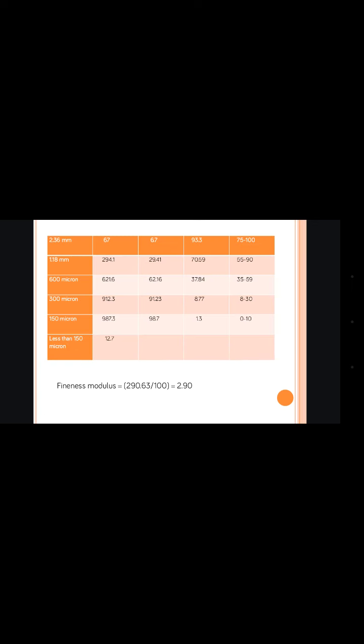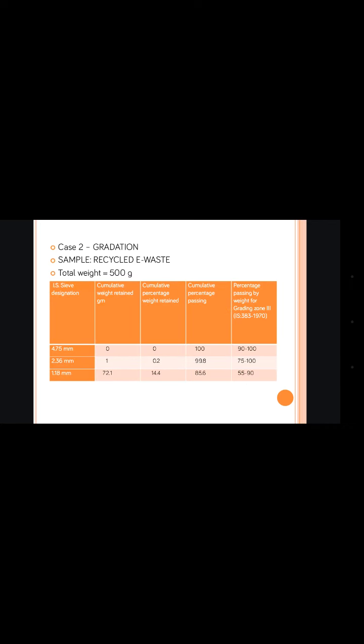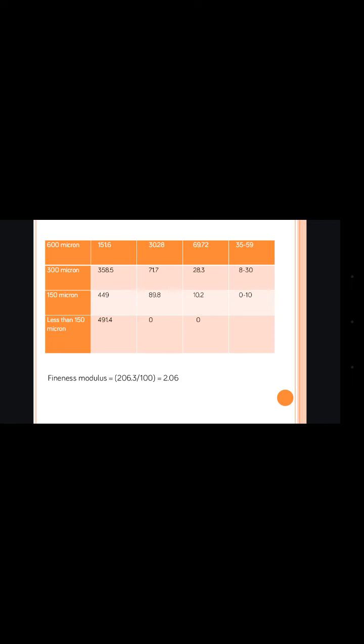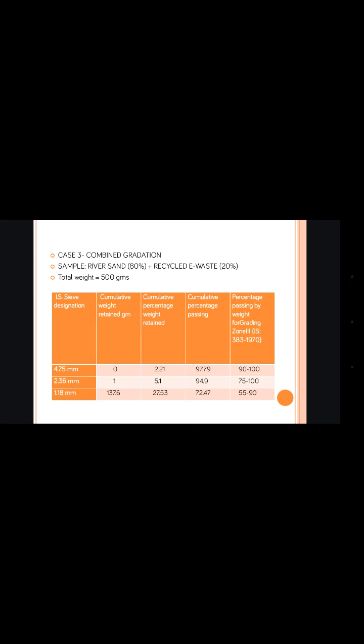The sieve analysis was taken for various cases. The first case was for river sand. The fineness modulus obtained from this is 2.9. In the second case, the gradation was taken just for recycled e-waste, and the fineness modulus was about 2.06. In the third case, we combined the gradation. We took 80% river sand and 20% recycled e-waste.